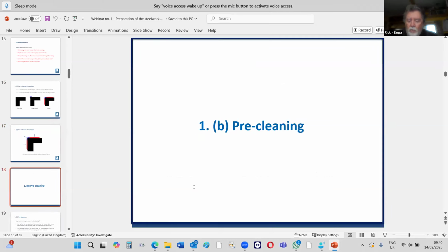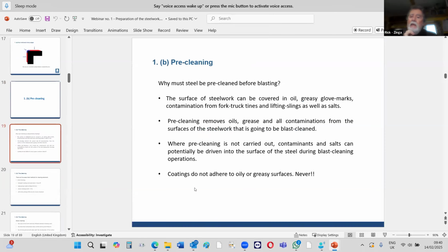Okay, after you've done all your work, you've got your pre-cleaning. I think we cover the pre-cleaning. It's also with welding. If you've done any welding, you will have weld spatter, all those little spots on there. And we say, don't grind them off. Again, use a sanding disc with 36 grit, 40 grit. When you go over it, it cuts off all your weld spatter, leaves it nice and smooth, ready for blasting. And again, pre-cleaning is a vital stage, because no coating will stick to oil or grease. There's no coating in the world that will stick to that.